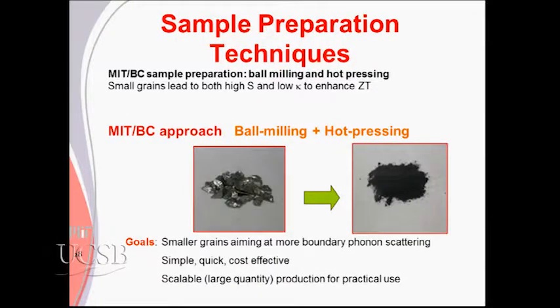And so the simplest idea is you take a material that's a pretty good thermoelectric, maybe bismuth telluride or something. And so that's the picture over here on the left. And you grind it up to make it as nano as you know how. And that's the picture on the right. And you see if that does anything. So those were the first experiments that we tried to convince ourselves that mass scale would also work. It wasn't enough to do it in the laboratory, but could we make something that was meaningful? So that was our effort at doing that.